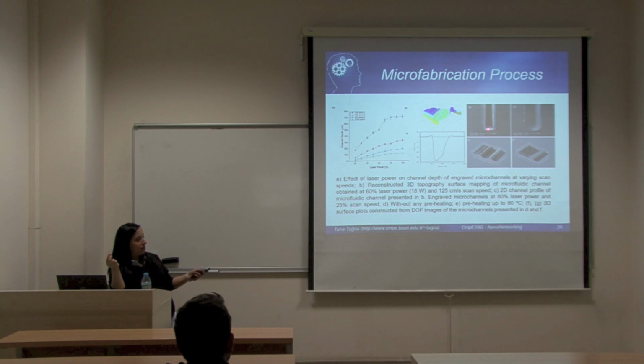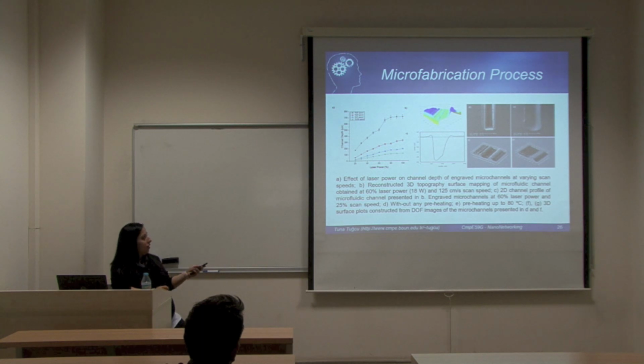And this is the optical microscopy image of two different channels we obtain. And these two channels are actually obtained because, as you can see, they're different from each other by just changing the laser power. So if I use 100% power, like a large power, I create really deep channels. Like the depth is quite high here, as you can see in this one. But if I decrease the laser power, then I lose the channel depth. But in this case, we have more smooth channel.